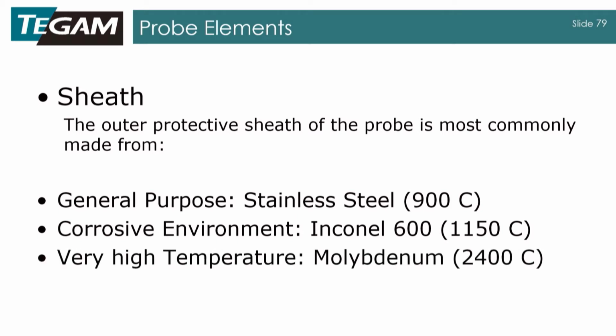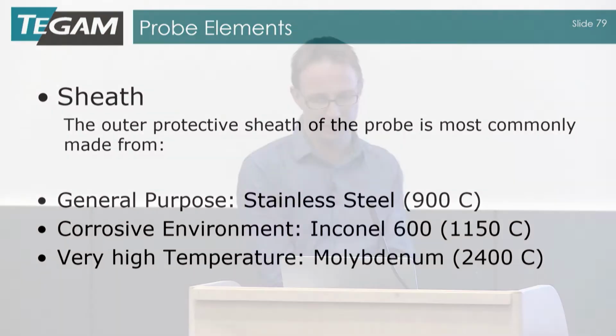And then lastly, for very high temperatures, molybdenum, I'm still working on the pronunciation of that, that'll take you up to 2400 degrees C. And that'll get you up to a high temperature, but because it has one of the highest melting points of all the pure elements, only tantalum and tungsten, as we talked about earlier, have higher melting points. It is a little rare and it is expensive, so if you're getting into an application such as this, you're probably going to be looking at spending some money. Like I said though, usually most temperature measurements falling under 900 degrees C, you're going to see that stainless steel.